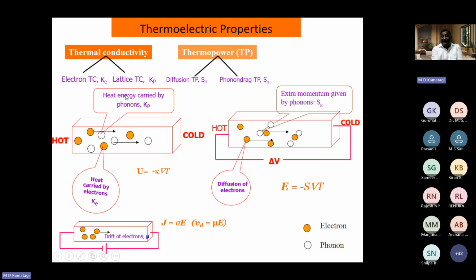So the ability of a material to carry heat we call thermal conductivity, and the heat is carried by both electrons as well as lattice vibrations. Therefore, we have an electronic contribution to thermal conductivity, which is the thermal conductivity carried by electrons, and the contribution from phonons to carry this energy. The electron thermal conductivity is sensitive to the composition of the material as well as the scattering centers and the electron concentration. And lattice thermal conductivity is sensitive to phonon scattering as well as the material structure.